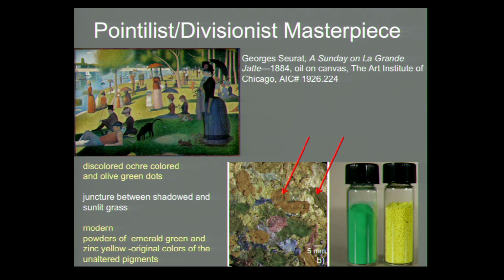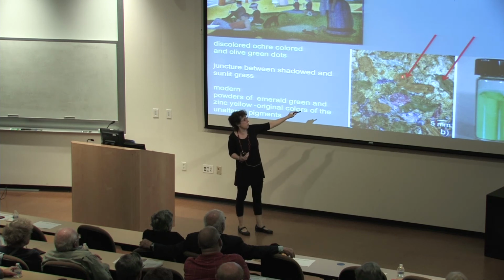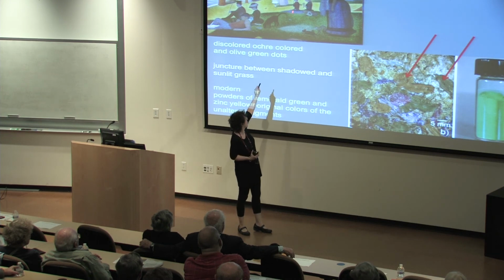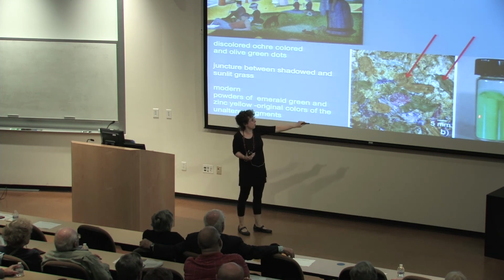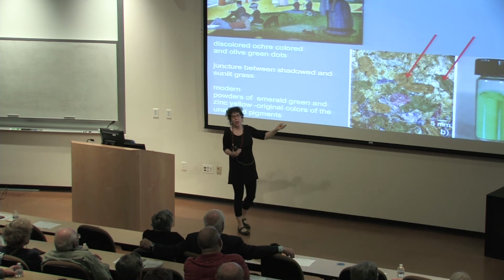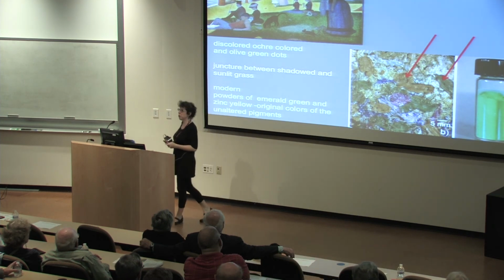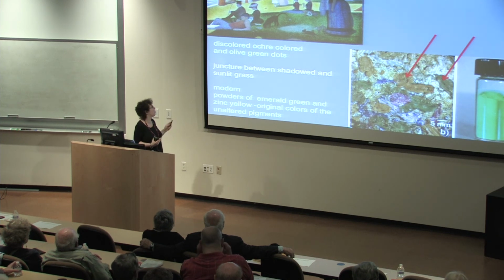So really what we're looking at here is just an exceptional pointillist or divisionist masterpiece. And unfortunately, if you look very closely at this painting, right at the interface from where the grass is in shadow to where it's in sunlight, this is what you see: what was originally a very bright yellow pigment, and look at what it looks like now, it's kind of this ugly ochre brown color. And then the green points were made with the emerald green, and you can see how it's turned this unpleasant olive color. And so there's really been some dramatic shifts in this work over time.